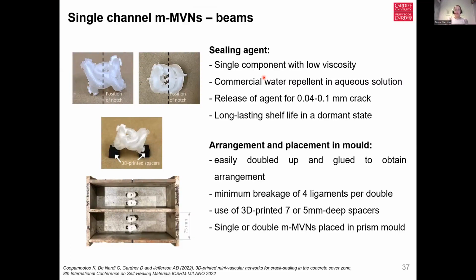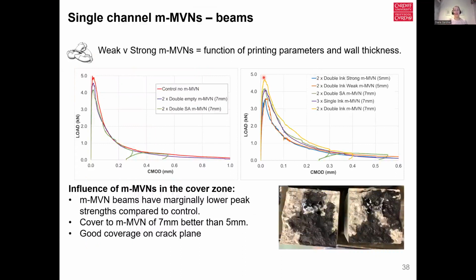And then we can, say, place these in molds and test them in exactly the same way we've tested our prior vascular networks. And what we saw, again, ensuring that we don't have any negative impact on the performance of our host material by including them within the material itself. We saw that the beams with these mini networks in have marginally lower peak strength compared to the control, although nothing really to worry about. We had better response out of those which are placed at 7mm away from the surface rather than 5mm. And also we had good coverage on the crack planes. You can see bottom right on the screen, we have clear evidence of this ink flowing out of these mini vascular networks.